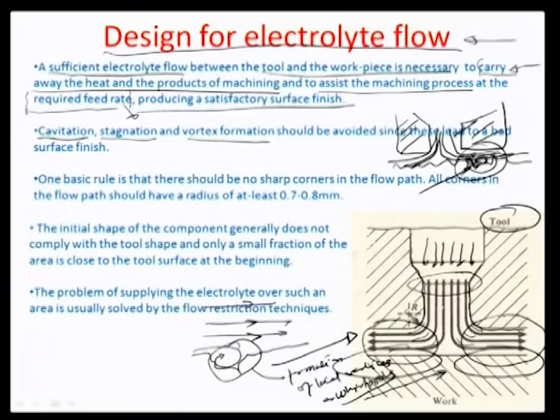Well, this can be dangerous to the ECM process because, number one, the local conductivity here is really a function of the amount of debris which is coming into this so-called local whirlpool. We can assume that the debris gets confined here in this particular zone, it does not get moved ahead. The remaining debris which is generated from, let's say, this surface or the other surfaces here would get carried away, but this local debris here does not go ahead anymore. Okay. So there is a change in conductivity, there is a change in machining rate, there is a change in so many parameters which are associated with this vortex formation.